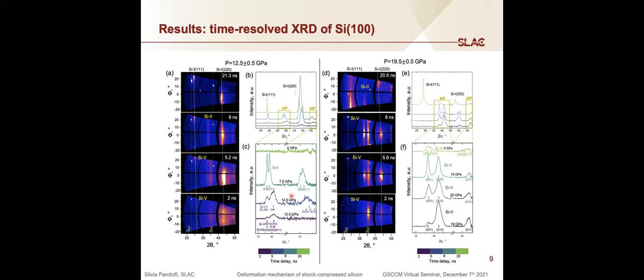And then from this pressure, because the samples that we were using were thinner, 43 micrometer thick, when we start probing later times, so around 8 nanosecond time delay, we already start seeing a release in the sample. And what's interesting is that upon release, we see very well crystallized silicon 2. So a lower pressure, high pressure phase that is observed during decompression, but is not detectable after complete release.